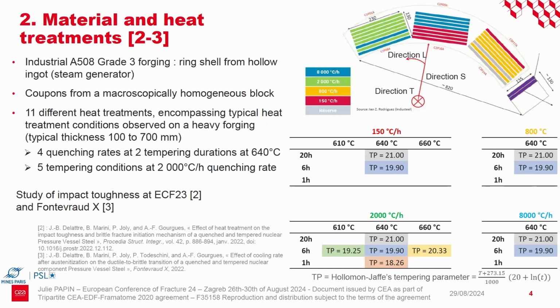The material studied is an industrial A508 grade 3 forging from a ring shell from a hollow ingot of a steam generator. And coupons were extracted from a macroscopically homogeneous block. This presentation deals with 11 different heat treatments encompassing typical heat treatment conditions observed on a heavy forging, with typical thicknesses between 100 and 700 millimeters.